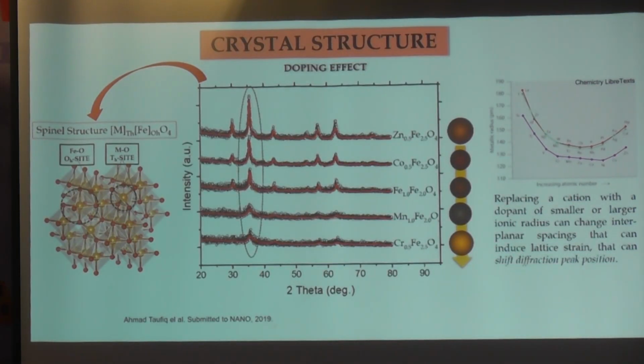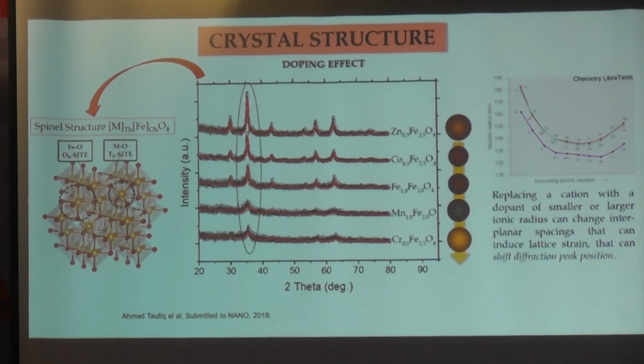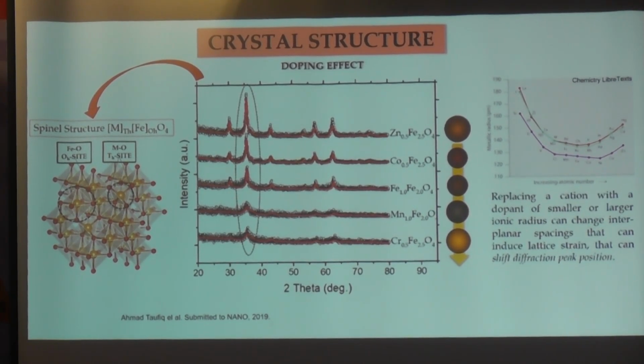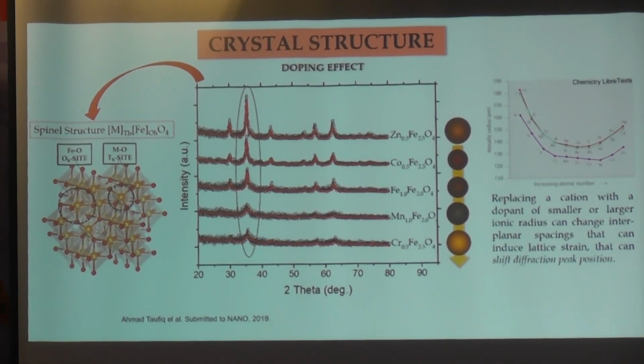Mn, zinc, or other elements replacing Fe2+ or Fe3+ will change the lattice parameter because of the different ionic radii. And the second, the big effect after changing the lattice parameter and crystal volume and also the crystal structure, is that because of the different magnetic spin of Fe2+ or Fe3+ compared with the other element, for example manganese, the magnetic character, especially the saturation magnetization, will change significantly.